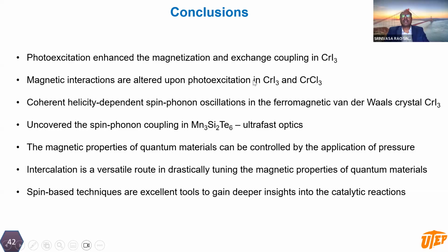And we have shown that on 3 or 4 independent compounds such as chromium iodide, chromium chloride, and manganese silicon telluride, as well as chromium sulfur bromide. We also applied pressure as a tuning knob, and we have shown that it is possible to manipulate the Curie temperature as well as magnetization on this compound by applying pressure from 0 to almost 25 gigapascal.